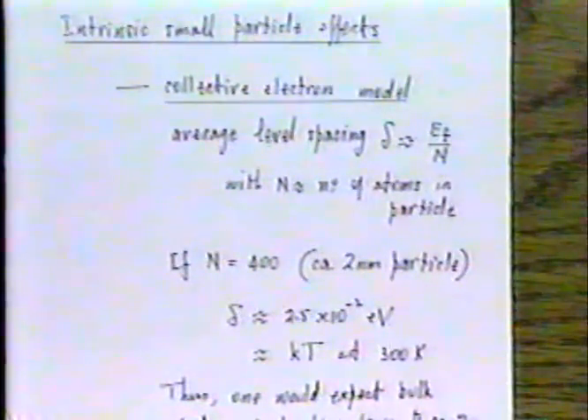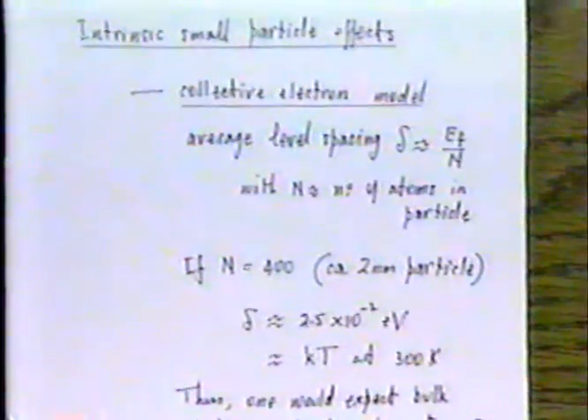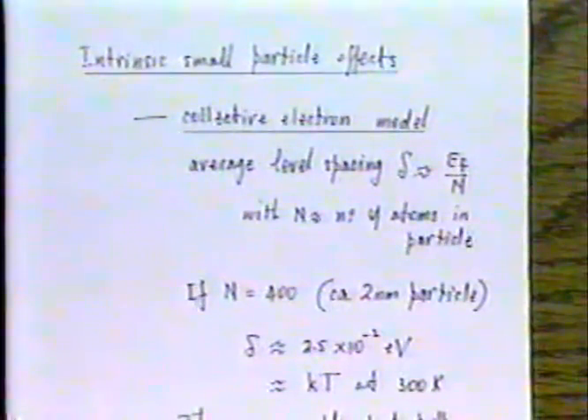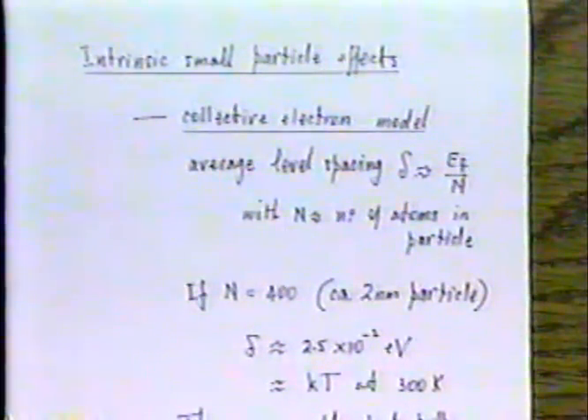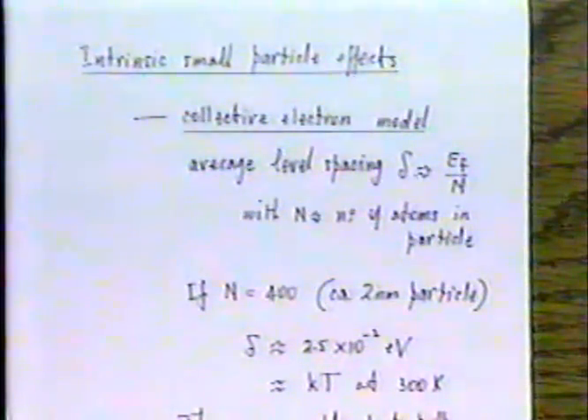The work function of a metal is the analogue of the ionization potential of a single atom. Suppose I take a single atom of platinum and remove an electron. The work done is the ionization potential, the energy required for the ionization process. If I take a lump of platinum and remove an electron, the work done in removing the electron to infinity is called the work function. And generally speaking, with metals, the ionization potential of a single atom is considerably in excess of the work function.